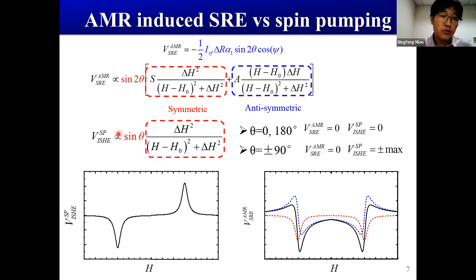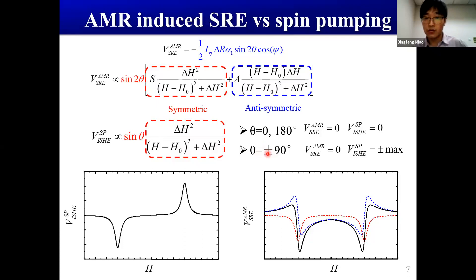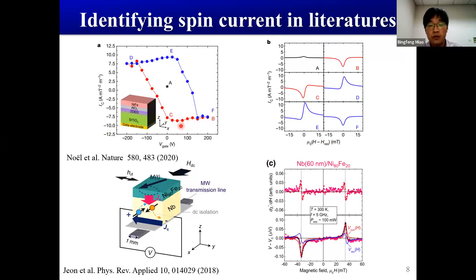On the other hand, the spin-pumping-induced inverse spin Hall effect has only a symmetric Lorentz line component and scales with sin(θ), which means it changes sign with the magnetic field and reaches maximum when theta equals 90°. It is generally believed that when experiments are performed with the field perpendicular to the stripe (theta = 90°), if one observes a symmetric line component that changes sign with reversing magnetic field, this is attributed to spin current. This criteria has been widely used in the literature.